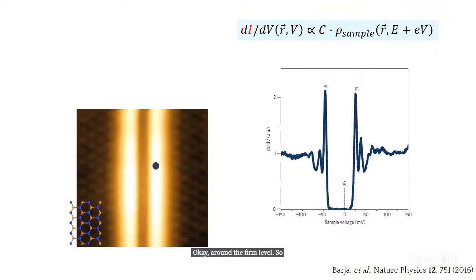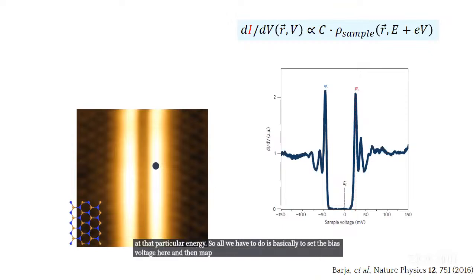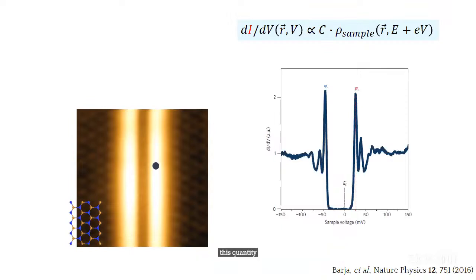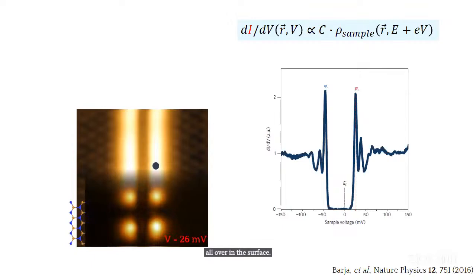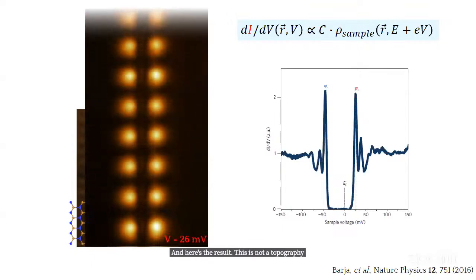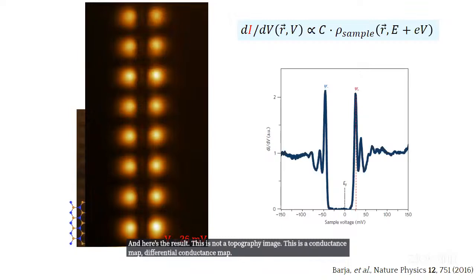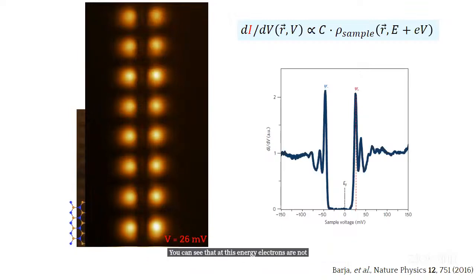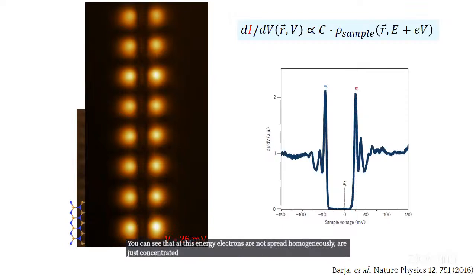Imagine that we wanted to know the spatial localization of this peak. That peak is located at 26 millielectron volts. So what's the spatial distribution of the charge at that particular energy? All we have to do is set the bias voltage here and then map this quantity all over the surface. And here's the result. This is not a topography image. This is a differential conductance map. You can see that at this energy, electrons are not spread homogeneously, they are just concentrated here. This is just an example.